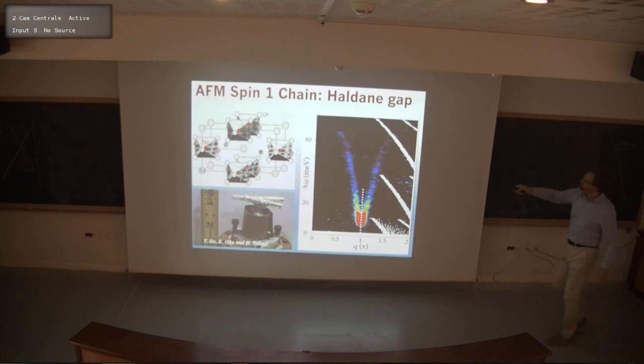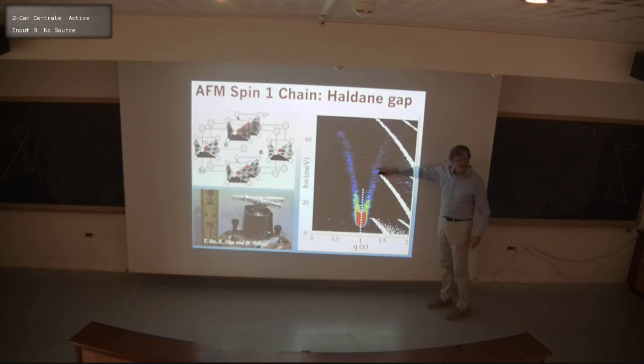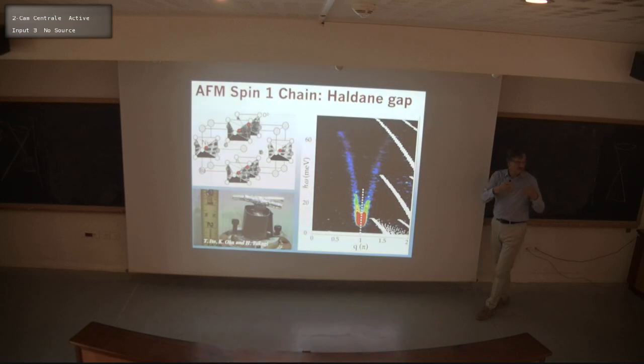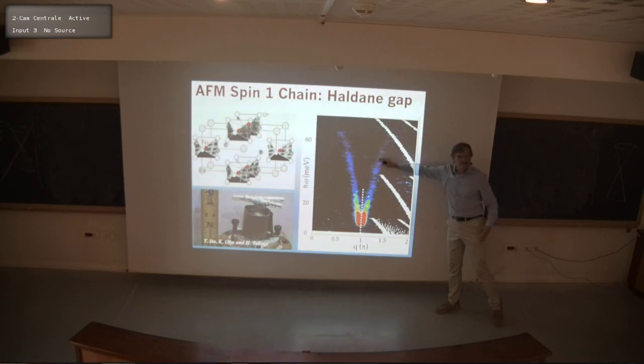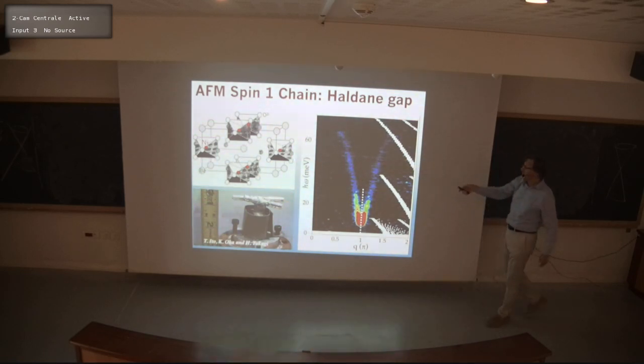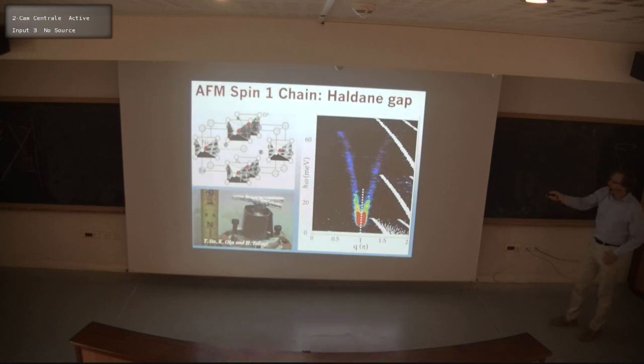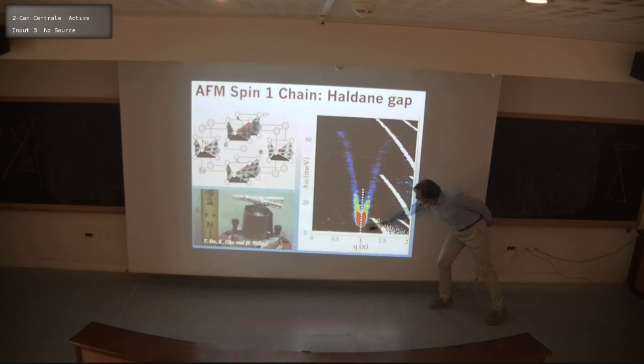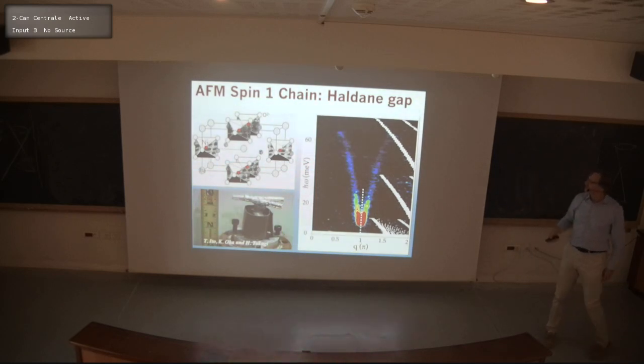Now you might say, well, this still has some sort of width, and what's he talking about, but that's actually an experimental resolution effect, and if you gave me beam time, I'd be able to find an instrument that could tighten this resolution, and I'd get a sharper and sharper mode. We really think this is a resolution-limited, coherent, magnon-like excitation. And the other thing is that here we actually have a gap in the excitation spectrum. There's an energy range here where there are no excitations available, and that's called the Haldane gap in the excitation spectrum of this compound, in this case yttrium barium nickel oxide.